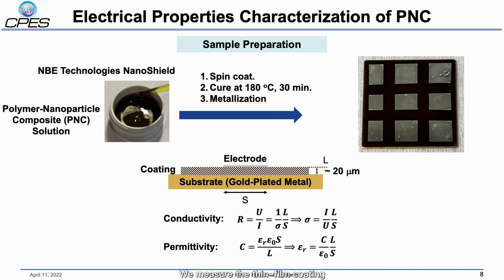We measured the thin film coating thickness to be around 20 micron. And then we did the PVD process on top of the coating to form a layer of metallization. This metallization will serve as electrode when we do the electrical characterization later. Then we use this sample to measure the IV and CV characteristics of the coating material. From the IV, we should be able to calculate the conductivity versus the applied voltage, which can be translated to the conductivity versus electric field. And for the permittivity, it is the same. We can use the CV curve to calculate the permittivity.